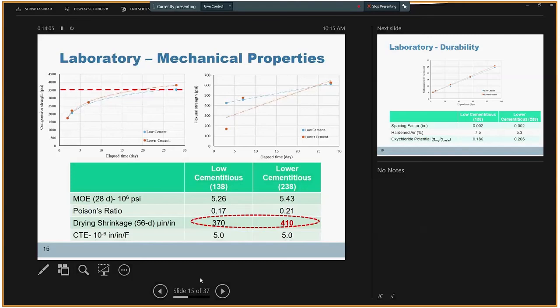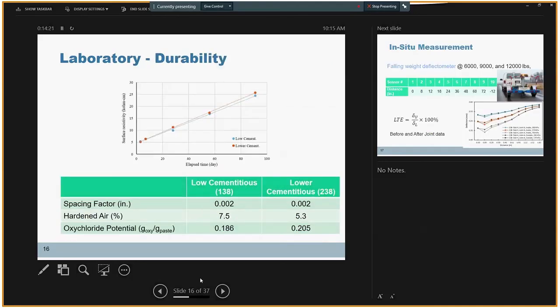However, because we had a higher water cement ratio in this mixture, we had a slightly higher drying shrinkage value for the concrete with lower cementitious material content. Other than that, the mechanical properties were comparable for the two concrete mixtures.